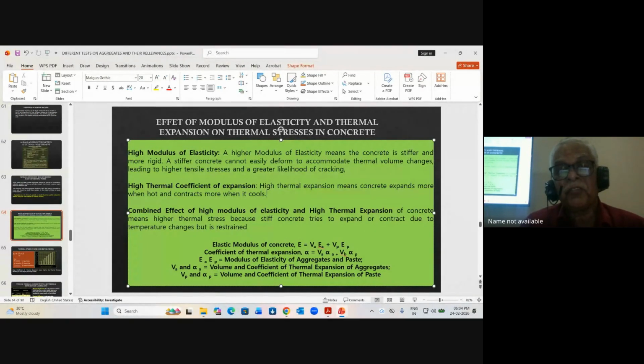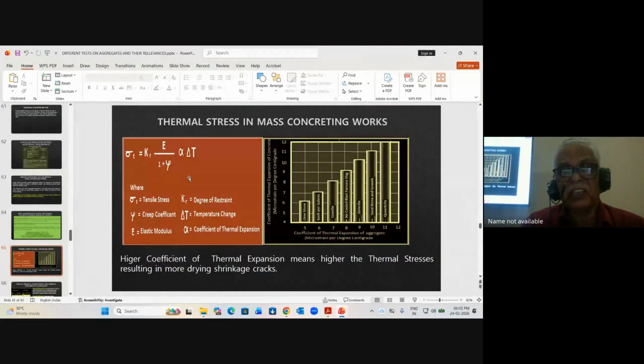Higher thermal coefficient of expansion means the concrete expands more when hot and contracts more when cool. When they are combined, temperature stresses are found using this equation. The thermal stresses in mass concrete also depend upon the thermal expansion of the aggregate. This chart shows thermal expansion for limestone, granite, and air-cooled slag - this is a typical example.